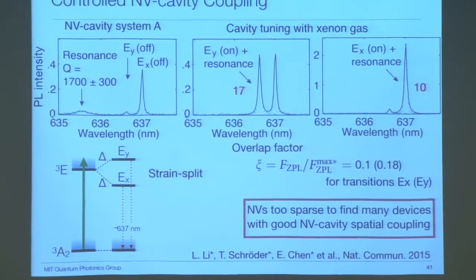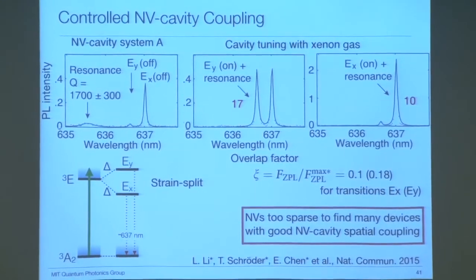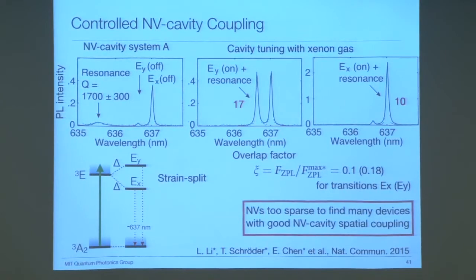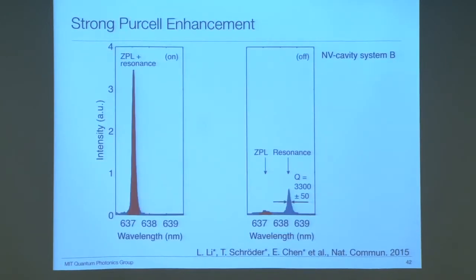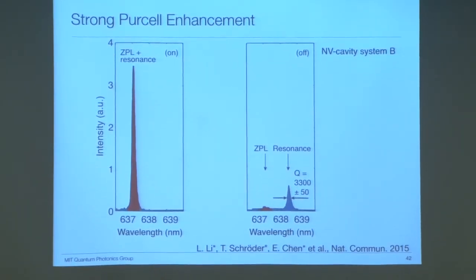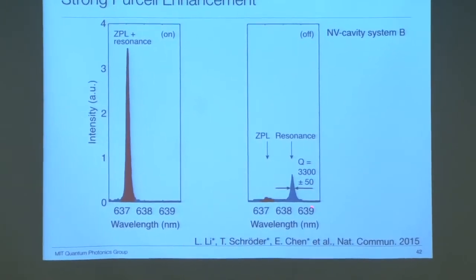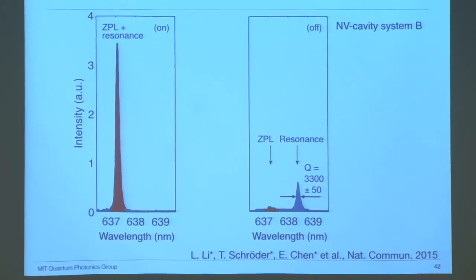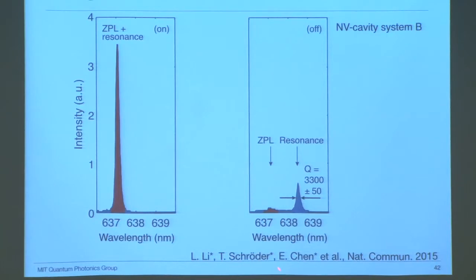So to solve this problem, we have prepared a larger sample with 10 times higher NV density, in which we find an NV cavity system B, with an optical quality factor of about 3,300. And this is a ZPL that is off resonance. And this is the ZPL on resonance with the cavity. And as you can see, there is a huge difference between the ZPL on resonance and off resonance.